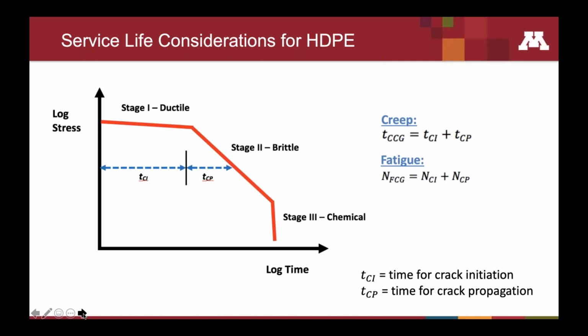So we do not have these high stress failure concerns. However, our primary concern with regards to service life for these pipes is those stage 2 failures. Stage 2 failures will occur at low to moderate stresses and after a long period of time. And what we wanted to do is to make sure that period of time was in excess of 100 years for these applications. So we wanted to basically push that stage 2 failure curve out to the right to make sure we were in excess of 100 years.